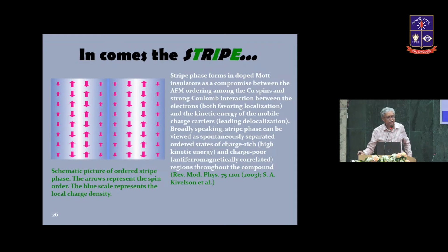Our understanding is the coupling we are seeing via the isotope exponent experiment is actually related to this charge and spin density wave. If it is not commensurate with the lattice, then what will happen when you have a charge order or spin order inside your system? There will be very strong coupling between electronic and lattice degrees of freedom. They will affect each other very strongly. This is a kind of electron phonon coupling constant, but the context is completely different because now we are talking about spin density wave and charge density wave. And this kind of order actually never helps superconductivity.